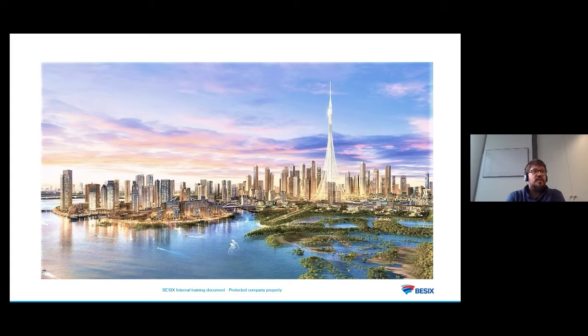And this is a really, really big challenge in terms of concrete technology and mix design, because first, the compressive strength is quite high. The concrete for the whole tower is going to be a C100, 115, way more than the C30, 37 that we are used to working with. So this is going to be a high-strength concrete that needs to be pumped at more than 800 meters in one go. So this is also something that we need to work on in the mix design. I will show you a few examples also of how we can deal with the pumpability of the concrete by choosing the right material.